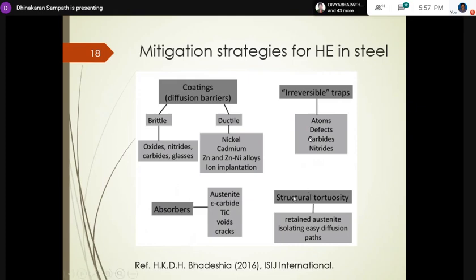So structural tortuosity, they introduce low diffusivity phases in ferrite. Ferrite is BCC, so it will have high diffusivity. They design the alloy in such a way that the diffusion is not taking place continuously.